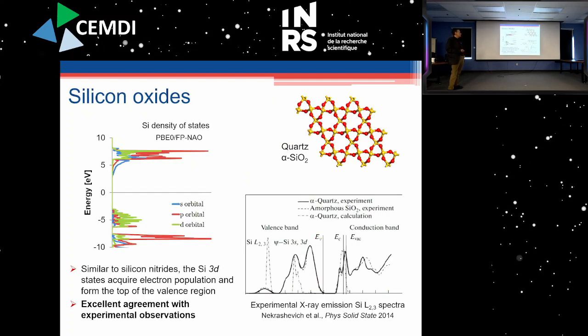We also looked at silicon oxides because, the interesting thing, quartz has been investigated extensively. So looking at the density of states for the silicon oxides, we found that very similarly to the silicon nitride, the 3d states acquire electron population. You can see this from the d orbital population here in the valence region.